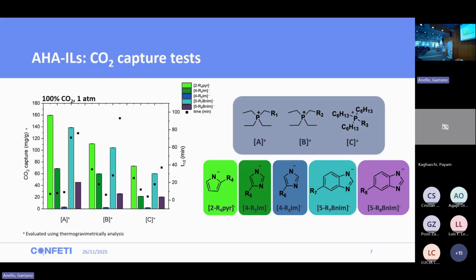You can observe that there are significant variations in the capture capacity between the anions and between the cations. For example, this blue imidazolate derivative shows the worst results, and this was due to the electron withdrawing effect of this R group, that is the nitro group. So we decided to discard it. Another observation was that the pyrazolate and the benzimidazolate have the highest capture in all three different families. And in the case of the cation, the smaller the cation, the higher the capture. This was due to the reduced molecular weight, which means that we can pack more active ions per gram of material.